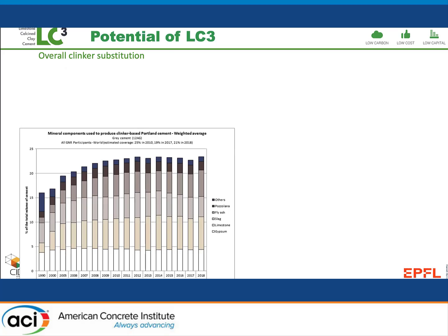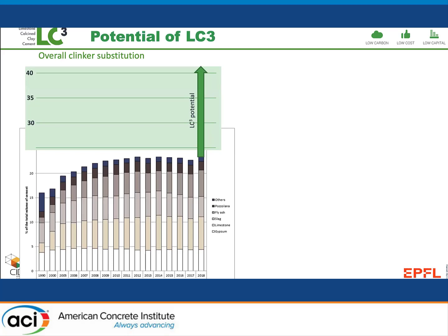Now, I think most people agree that from a technical basis, we could very easily go to an average substitution level of 40%. And if we did that with a mixture of calcined clay and limestone, we would save 400 million tons of CO2 per year. That's huge. That's like 1% of all global CO2 emissions. And that's a very conservative estimate because that is saying 40% substitution. And our recent work has really shown that probably we could go to double that. So probably we could go to 800 million tons of CO2 a year. I don't think there's any other single technology in the cement and concrete business that can deliver those kinds of CO2 reductions.